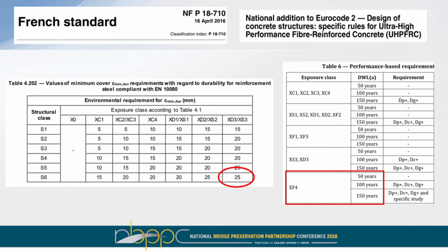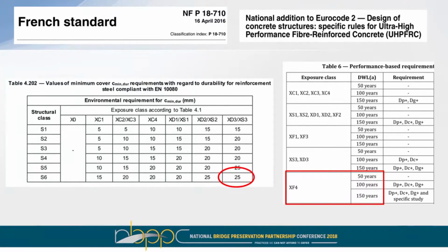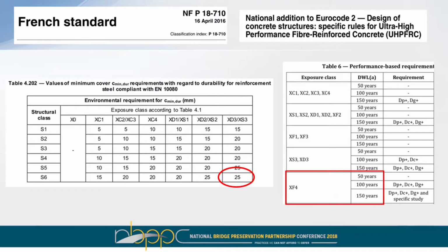In Europe, they've developed this technology a bit further than we have in the US right now. If I look at the French standard that has really adopted this technology, if you can read this, we're looking at the minimum amount of cover clearance that you need to put over a black rebar to satisfy a certain design lifespan. The table on the right shows three lifespans, 50 years, 100 years, 150 years, under various exposure conditions, with XF4 being an environment that has heavy freeze-thaw and salting effects. The table on the left tells you what your cover needs to be. And the bottom right box that's circled is your worst case condition. And what you see is 25 millimeters of cover.